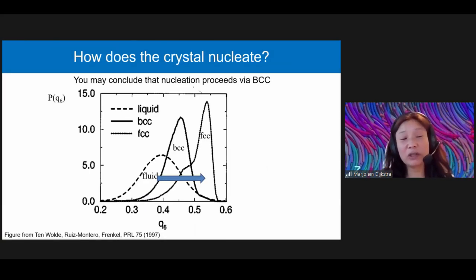If you plot, for instance, the distribution functions of the q6 values for a typical fluid configuration, BCC, body-centered cubic configuration, and face-centered cubic crystal configuration, then we see that the q6 value is relatively low in the fluid phase and it is high in the FCC phase. And naively, one would be able to conclude from this plot here that the fluid always nucleates via the BCC phase.